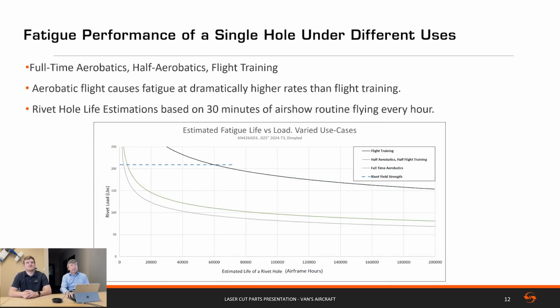This is an example of different use cases. So as we look at these reduction factors and convert, the aerobatic fatigue case is significantly more damaging than a more normal general use or flight training, which is more damaging than that. As we predict things and need to look at the fatigue performance of certain details and holes, the most dominant factor in that and when something will crack is how the airplane is used or abused. To be conservative, we assume a significant amount of aerobatics are used in the aircraft.